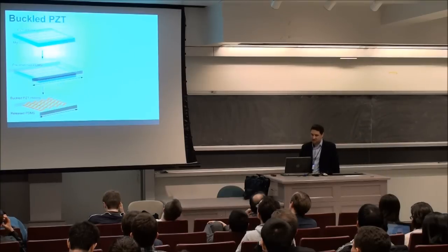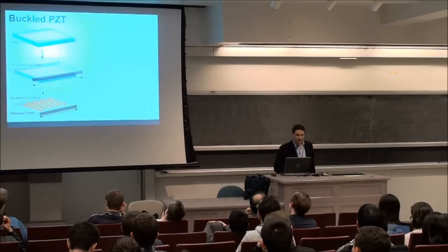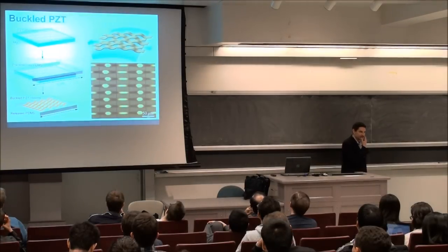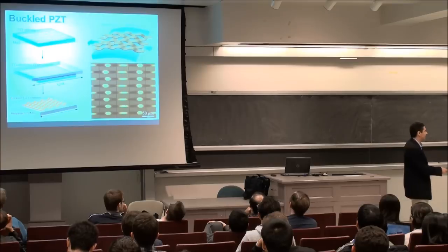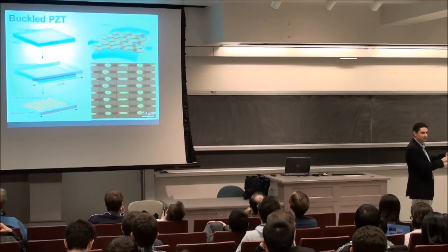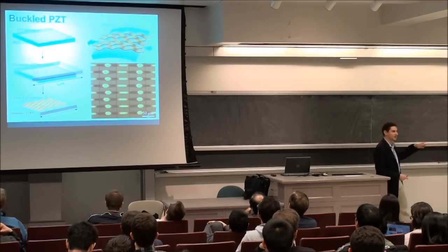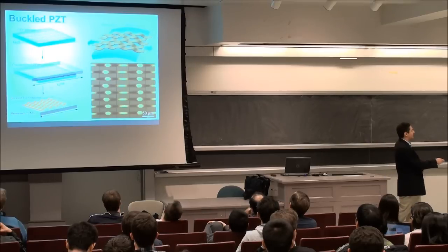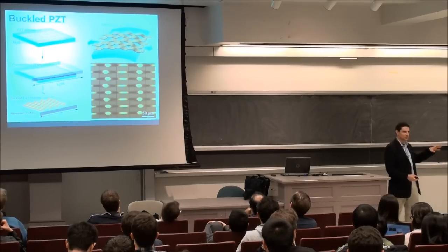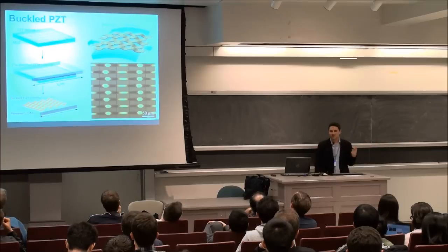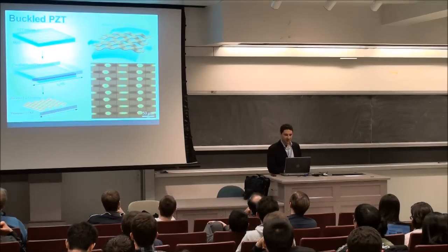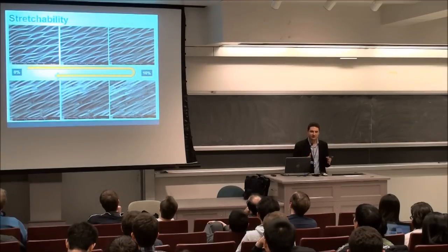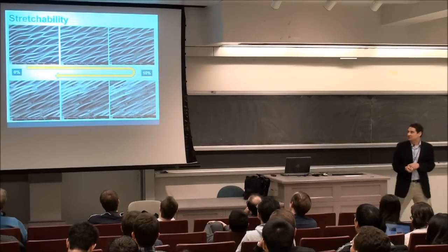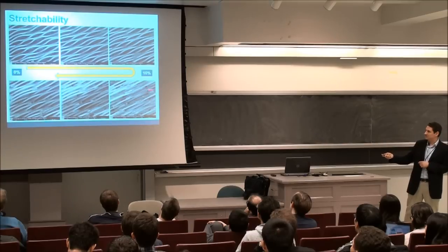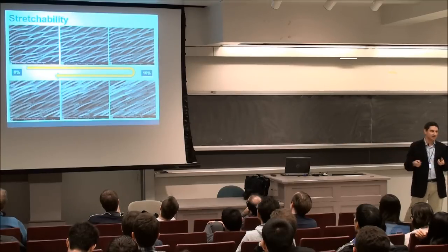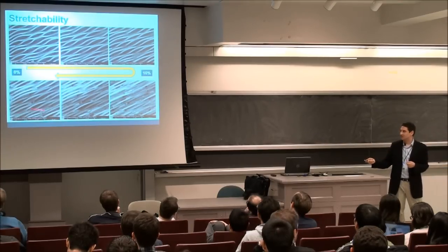Of course, PZT has a weird surface chemistry. So we can't do the same things that you guys do. We have to use other tricks, like, for example, patterning the PDMS here in order to get the buckles to be in phase with each other rather than out of phase, okay? But we can actually do this, because again, the PZT is so thin, even though the Young's modulus is so high, you can actually get these buckles to form in PZT. So now when you stretch it under the SEM, instead of it cracking up on the surface, you'll see that it actually will flatten down nicely onto the substrate, up to about a 10% stretching, and then you can release it and it'll buckle back up.